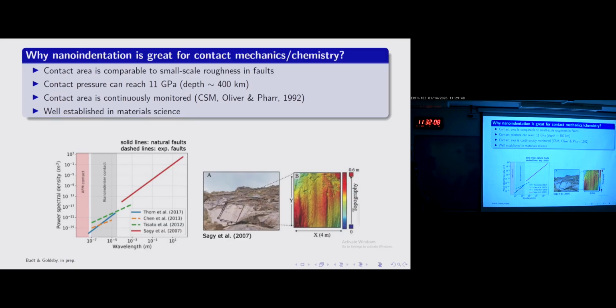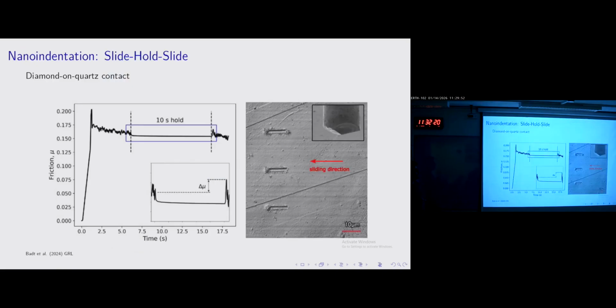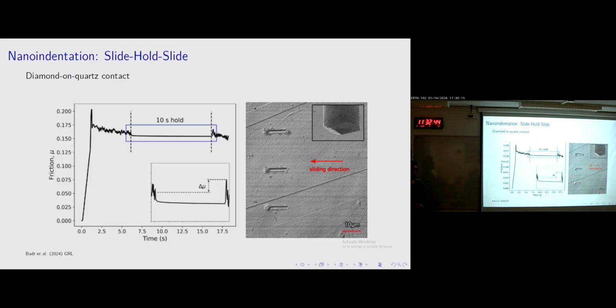So we have a really good instrument that can provide us a lot of high quality information that is typically lacking in traditional rock friction experiments. Okay, let's start off with doing some slide tests with a nano-indenter. We're running diamond on quartz, a diamond tip on a natural quartz sample, and that's the tip. And we can scratch the surface. You can see I can make the scratches going around any heterogeneities in the sample itself.